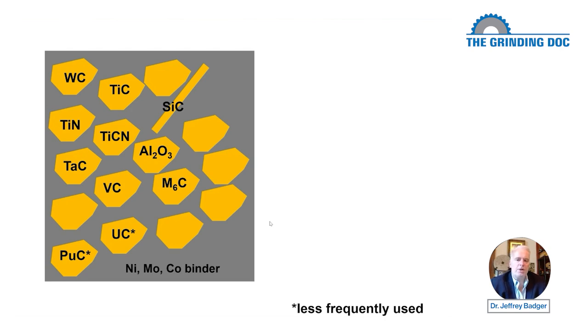Okay, so tungsten carbide doesn't really dull diamonds. There's some exceptions. If you grind with a water-based coolant, you will get some slow dulling. If you're grinding with a plated wheel, you'll get some dulling. But for hardcore material removal in tool grinding, round tools, flute grinding, and everything else, the diamond grits don't become dull and flat. Now the wheel loads, and that's what's nasty about tungsten carbide grinding. The wheel clogs and loads, but the grits don't become dull.